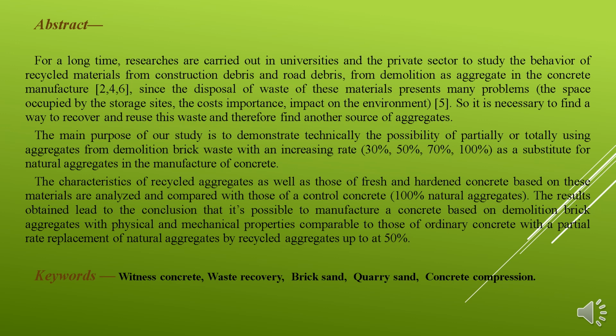The main purpose of our study is to demonstrate technically the possibility of partially or totally using aggregates from demolition brick waste, with increasing rates of 30%, 50%, 70% and 100%, as a substitute for natural aggregates in the manufacture of concrete. The characteristics of recycled aggregates, as well as those of fresh and hardened concrete based on these materials, are analyzed and compared with those of control concrete, 100% natural aggregates. The results led to the conclusion that it's possible to manufacture concrete based on demolition brick aggregates with physical and mechanical properties comparable to those of ordinary concrete, with a partial replacement of natural aggregates by recycled aggregates up to 50%.